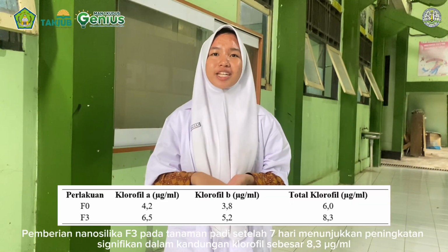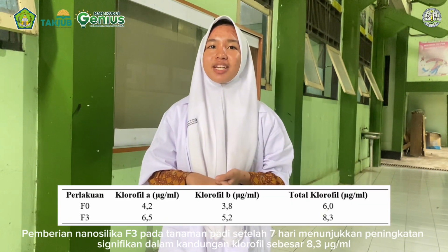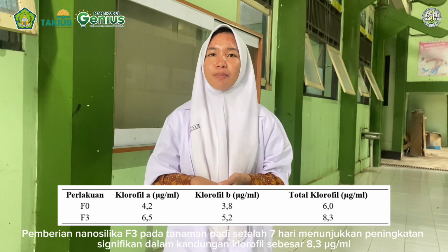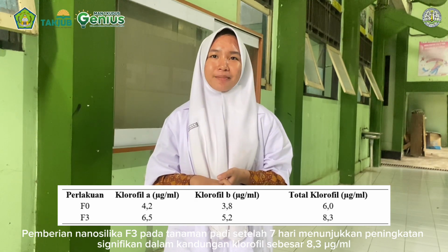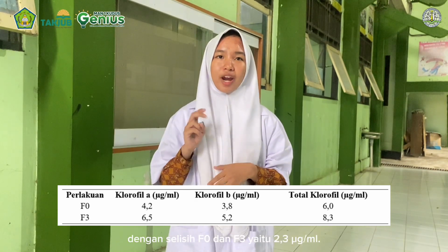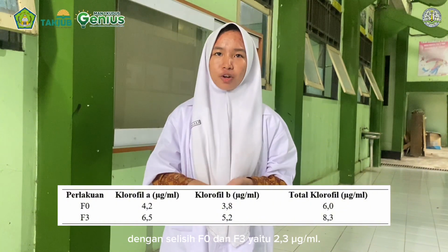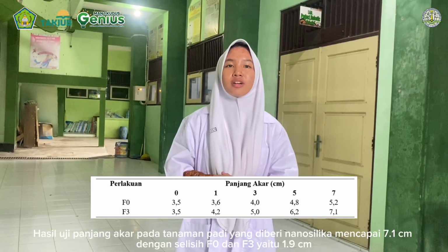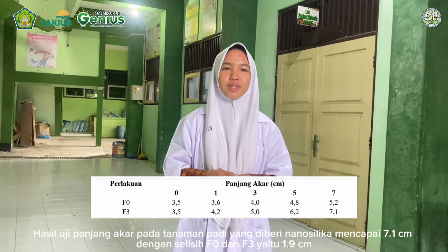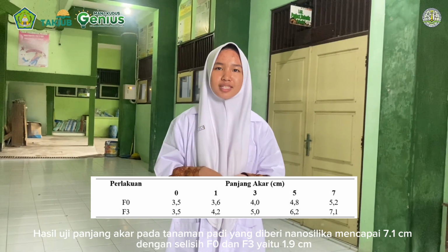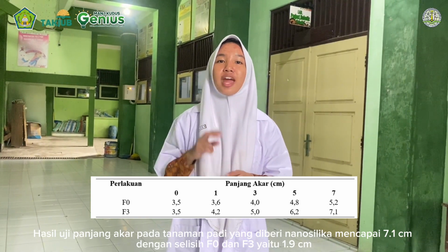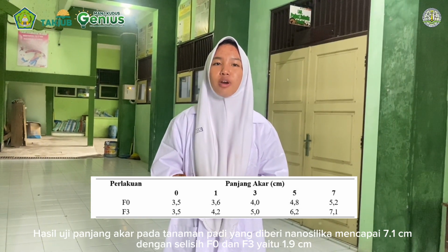The result of the chlorophyll content test by the UV-Vis spectrophotometry method, the application of F3 nanosilica to rice plants after 7 days showed a significant increase in chlorophyll content of 8.3 microgram per ml, with a difference between F0 and F3 of 2.3 microgram per ml. The result of the root length test on rice plants fed with nanosilica reached 7.1 cm, with a difference between F0 and F3 of 1.9 cm.